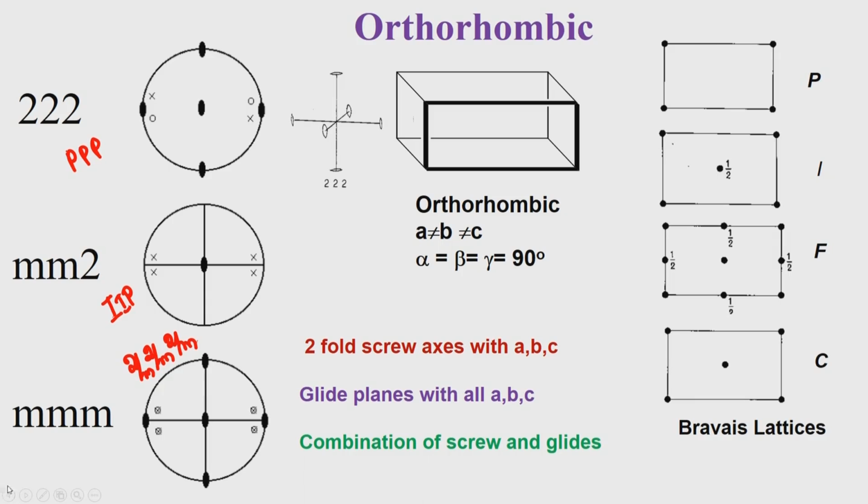So, whenever you see more than 3 mirror combinations coming, like for example, later you will see in the tetragonal system 4 by MMM, it actually means it is 4 by m, 2 by m, 2 by m. If you remember that carefully, in fact, it is part and parcel of your understanding this whole course, then you will never make a mistake. Okay. So, 3 proper rotations 2, 2, 2 now will take us to the point group symmetry 2, 2, 2.